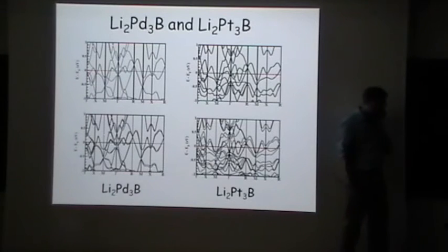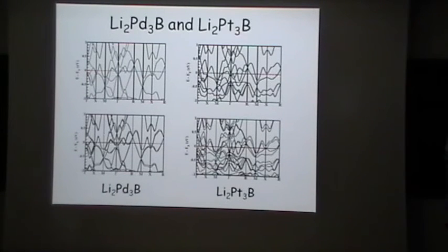So what I would suggest is you could introduce it as some sort of surface spin flip scattering, perhaps. Actually, Ilya, you did calculations of this type, no? Well, we did a calculation for the surface with no spin orbit, but I think the difference is that because it's a metal, spin orbit at the surface will be screened at the Thomas-Fermi length. Yeah, that's a good point. It will come exactly as Daniel says, as the boundary condition. So you can introduce spin flip processes at the interface, and that means the spin will not be conserved, but there will be no triplet component in the bulk. Whereas what is suggested in these talks is that there is a bulk property that stabilizes the triplet component in many situations, simply because you can't have just singlet. Yeah, the coherence length is just too big for this to be relevant for the bulk properties.